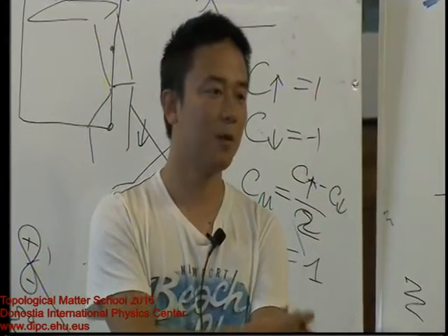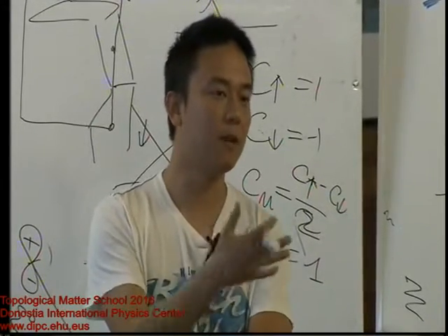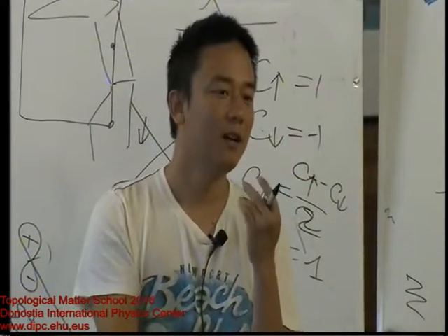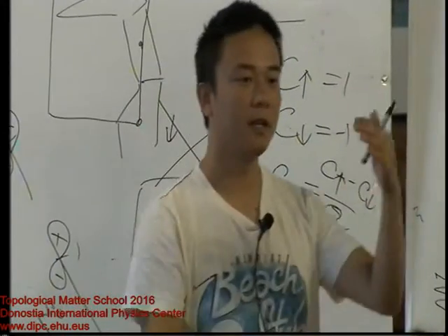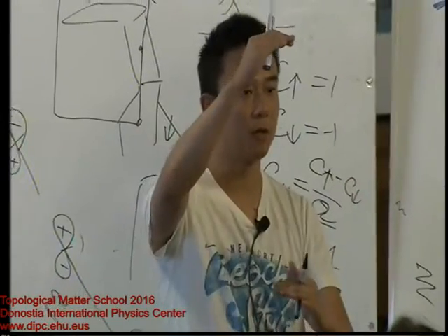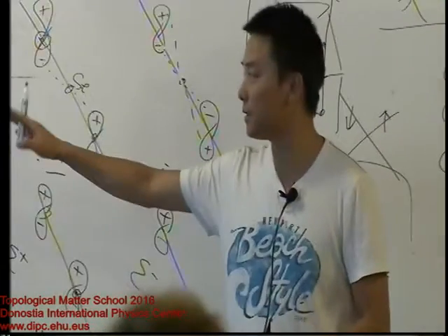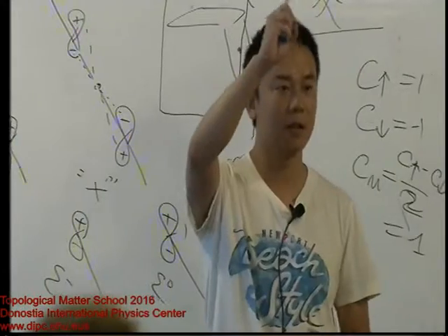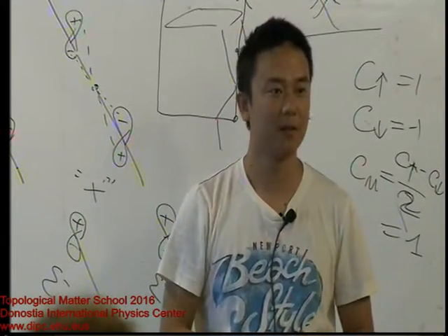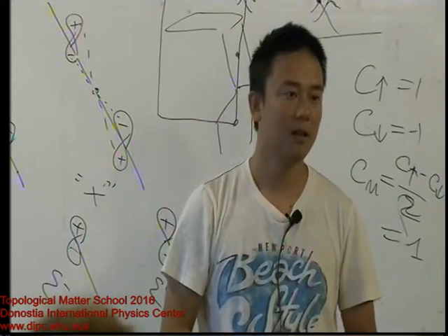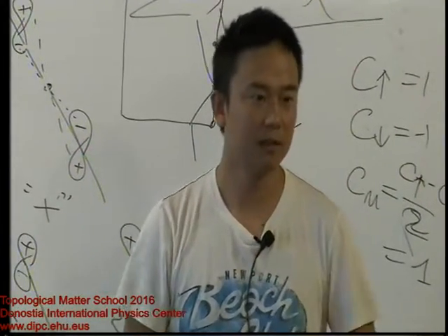Yes. And spin-orbit coupling is also sometimes involved in the band inversion. In bismuth telluride directly, it's spin-orbit coupling that causes the band cross. Well, in mercury telluride, it's slightly different, but it's another relativistic effect. So it makes the band inversion.